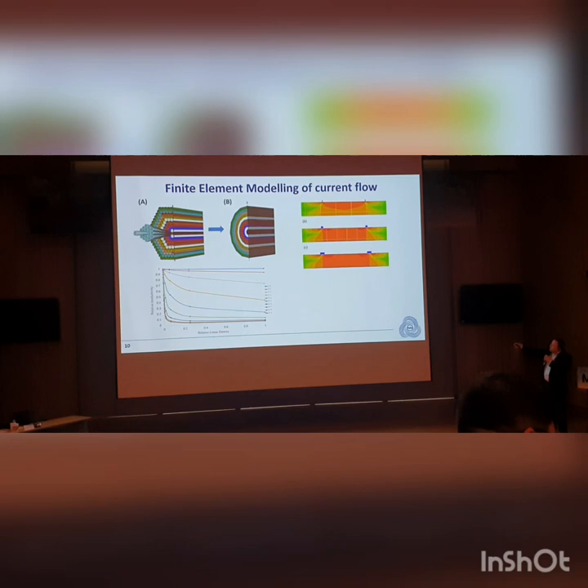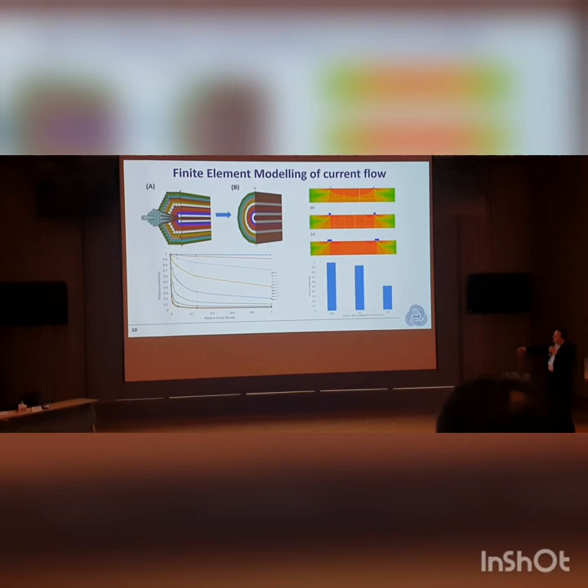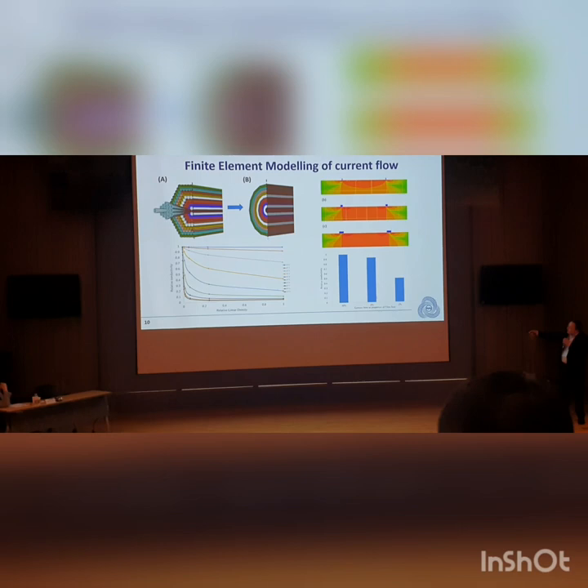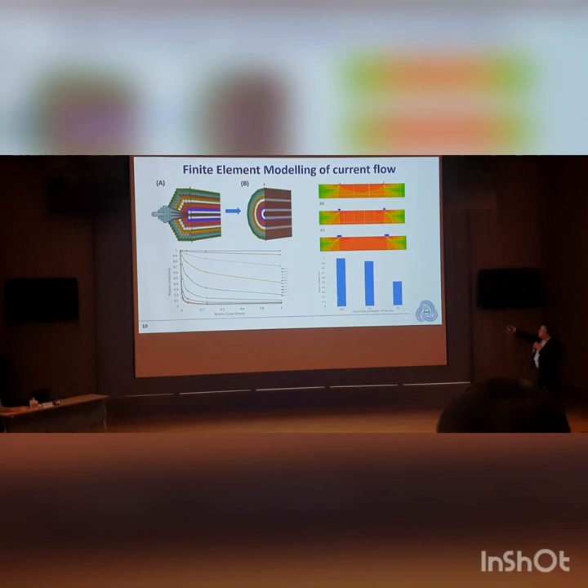There's also an effect of electrode size that's not often well known. If you're measuring electrical conductivity of fibers, the size of the electrodes in contact with the fiber matters. Looking at current distribution through the finite element model by varying electrode size, it makes quite a big difference in how far current penetrates into the fiber. If the electrodes are 10% of the fiber contact area versus 1%, you could get an effective reduction of conductivity by 50% — even though nothing in the fiber has changed. You have to specify your setup and electrode size, otherwise you're measuring a different conductivity.